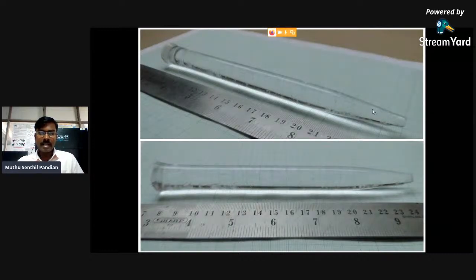This is the as-grown TGS crystal inside the glass sample. Here we have mounted the TGS seed at the bottom of the glass sample along the polar b direction. So this much of transparent crystal can be grown.